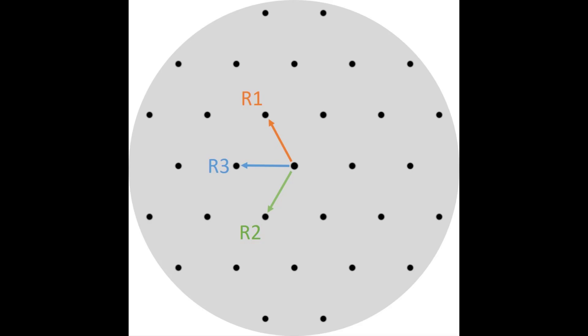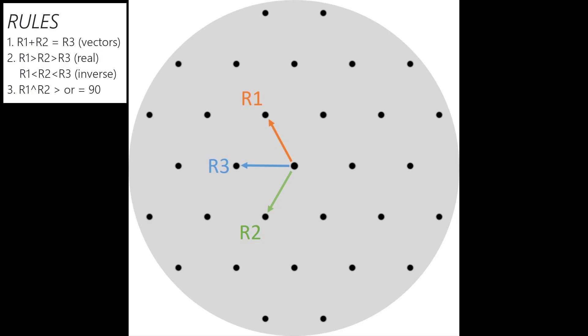Now let's talk about R1, R2, R3. I'm going to show two different patterns. Here's the first one and there are rules that tell us how to assign the different vectors to the spots. The first rule is that the vectors of R1 and R2 should equal R3. So in this example the blue line which is our blue vector R3 falls between the placement of R1 and R2. You can imagine adding these vectors. The orange line plus the green line gives us the spot where R3 is.